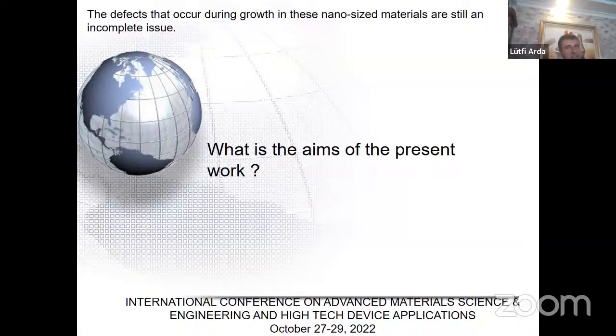Which is the aim of the present work? Let's explain this. We focus on the relationship between the synthesis parameters, the temperature and the growth time, and the role of defects on structural and optical properties. We synthesize the zinc oxide nanorod using a hydrothermal route at various temperatures and growth times. The defect density of zinc oxide nanorod manufactured by the hydrothermal route is investigated by the Gaussian decomposition of the PL spectrum. PL means photoluminescence spectrum. We also investigated the changes systematically in the optical properties concerning the structural and defect evolution of this compound. We observed that optical properties, including visible transmittance and the band gap, are easily organized by changing hydrothermal growth time and the temperature.